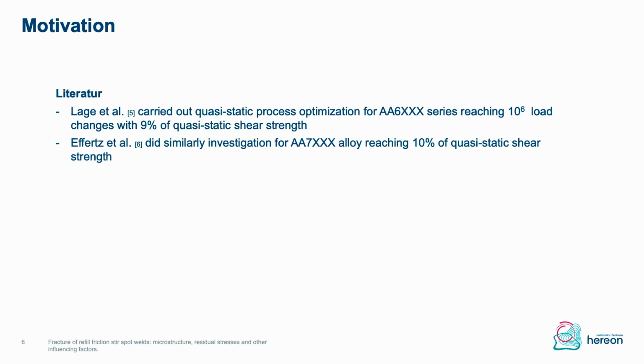But it used to be that they do, like Lage et al. did, quasi-static process optimization for here 6000 series, and then took those welding parameters for fatigue testing, and they were able to reach only 9% of quasi-static shear strength. Effertz did some similar investigations for 7000 alloy, reaching 10% of the quasi-static shear strength. So basically, the approach to do a quasi-static optimization and try to improve the fatigue life is not working very well.